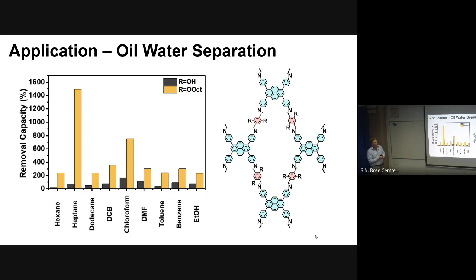What is the maximum length in the structure, the diameter? It's 2.4 nanometer, the largest one. How do you remove the absorbed liquid? We dry it in the oven, so this is not an absorption measurement. If you want to apply this as a membrane system, then the option is also permeability. In our case, we just heated it out again. We just wanted to do something with it, to understand the material a bit.